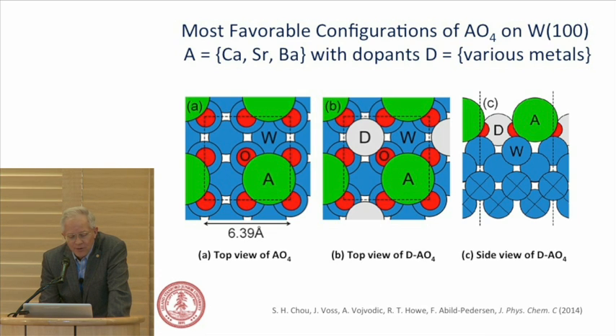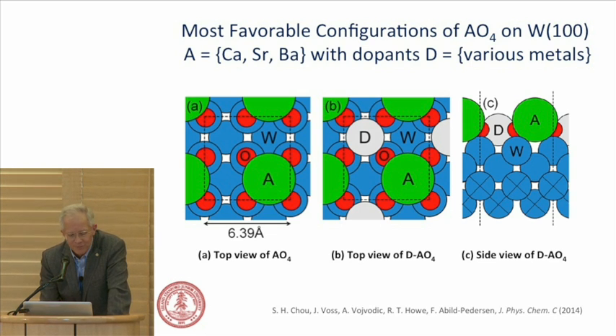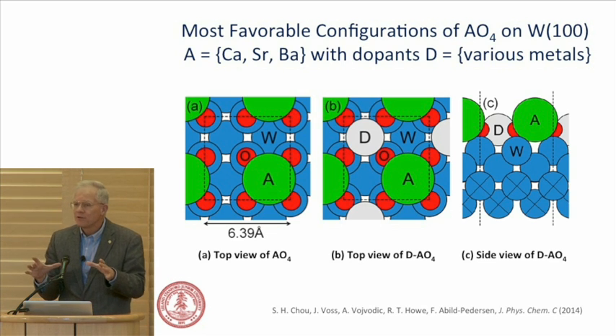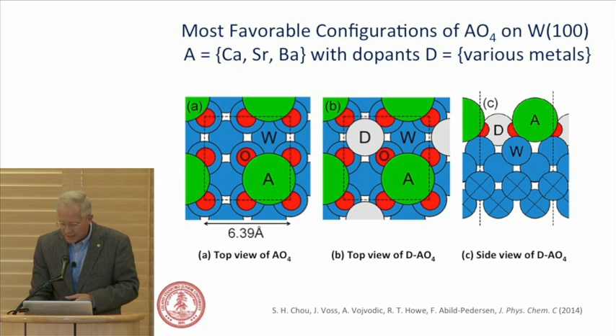So focusing on this set, we still have a lot of simulation to do because we have our basic alkali earth, which is calcium, strontium, or barium, and we can dope that. In the literature, there's a lot of work on adding things, lithium and other metals. So what is showing here is a virtual atom that could be a blended composition of the pseudopotentials of these 3 atoms as a shortcut. And obviously, the unit cell that's being simulated is important to minimize that.